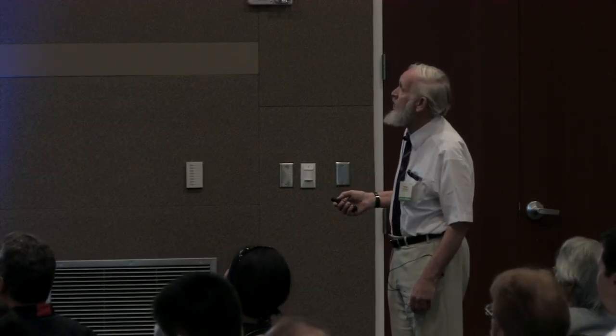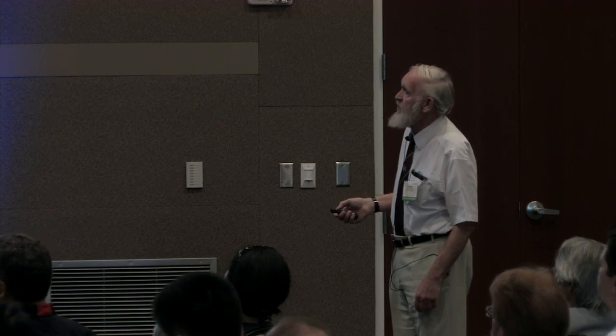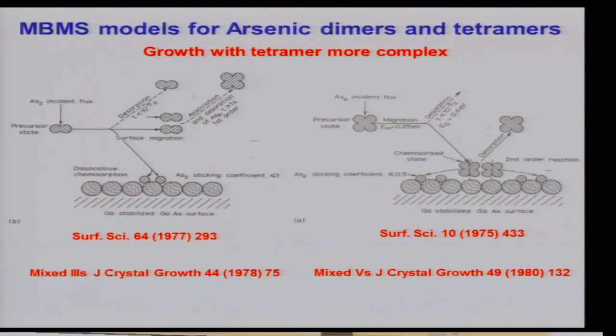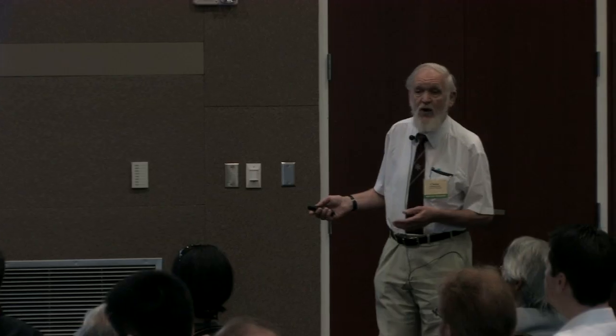Okay, so all of that led to the development of the models for growth of gallium arsenide. Essentially, this one reproduced what John Arthur had done earlier, showing that the sticking coefficient of arsenic was 1. It's more complicated with the tetramer, and it's a much more elaborate surface reaction here. It's a second order reaction. Bruce was in his element with this. He was a chemist by training. He was only ever interested in MBE as a route to understanding chemistry. That was his forte. We went on to look at mixed group 3 elements and mixed group 5 elements. So we covered pretty well the range of 3-5s.